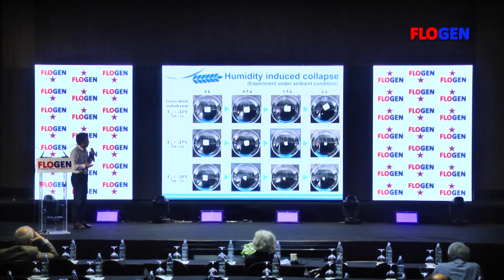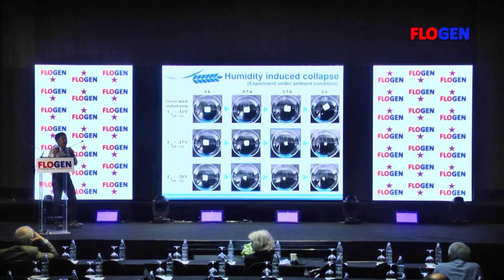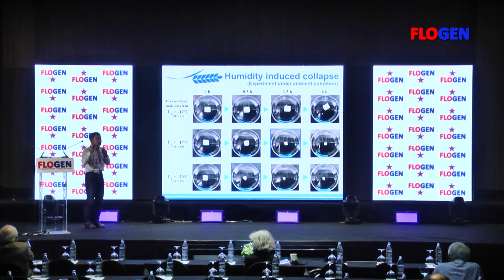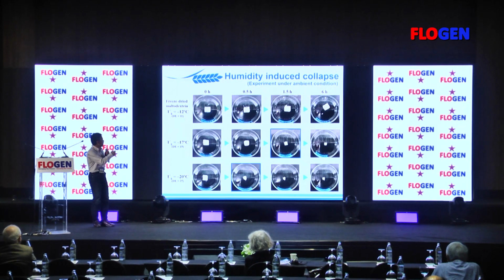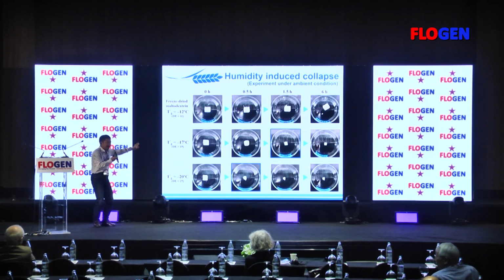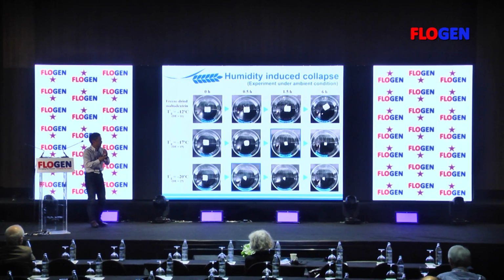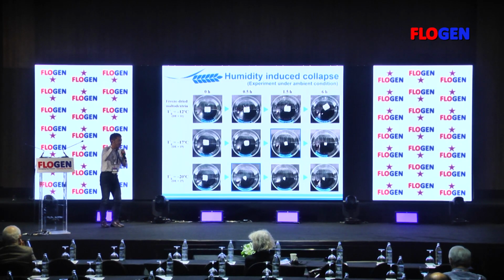So this is experimental data that my student carried out several years ago. He freeze-dried maltodextrin. Maltodextrin is not a pharmaceutical thing. It's a kind of foodstuff, hydrolyzed from starch. Depending on the degree of hydrolysis, we can control the glass transition temperature, so it's very useful for experimental purposes. So I used it. One has a higher glass transition temperature, and another has a lower glass transition temperature, which means it easily starts the glass-rubber transition.